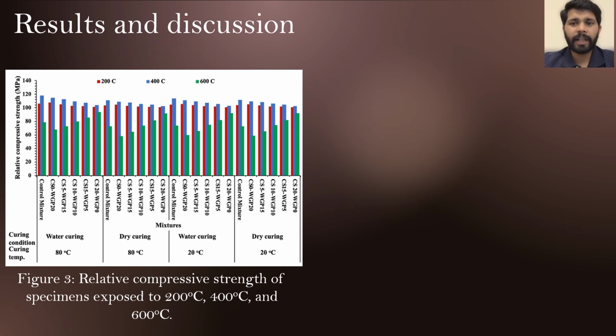Figure 3 illustrates the relative compressive strength of specimens exposed to higher temperatures such as 200, 400, and 600 centigrade. At 200 and 400 centigrade, the compressive strength increased, which can be attributed to evaporation process, which generates friction between the layers of mortar, and hence more load is required to break the sample. Plus, hydration rate also increases at higher temperature, leading toward the thick formation of calcium silicate hydrate gel and increases the strength. However, the decrease in compressive strength at 600 centigrade can be attributed to the decomposition of hydration product. But it is interesting to know that at 600 centigrade, the compressive strength of purely Cenosphere based mixture neither decreased nor increased due to its excellent thermal stability.